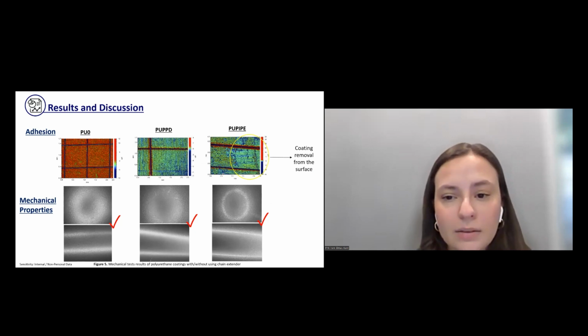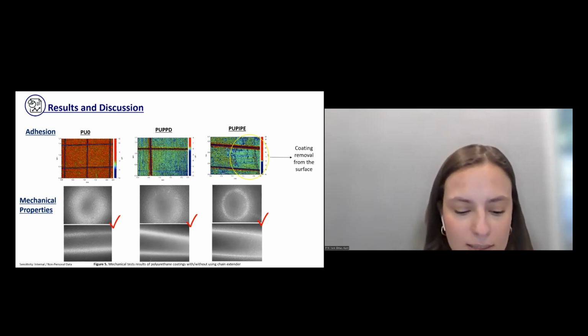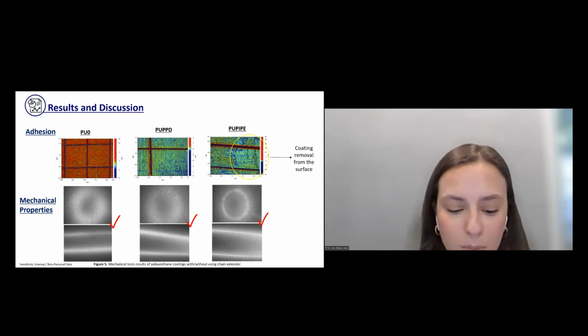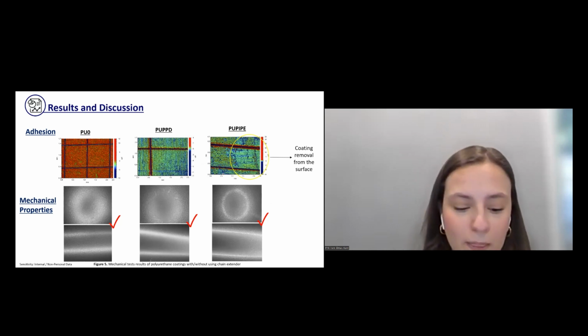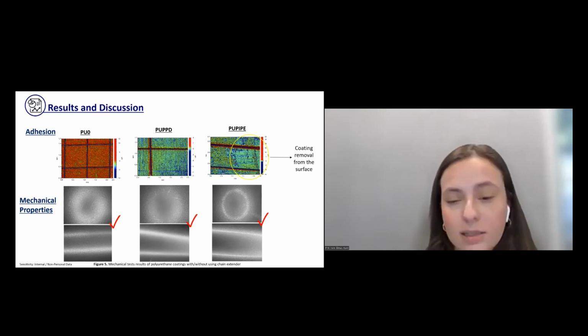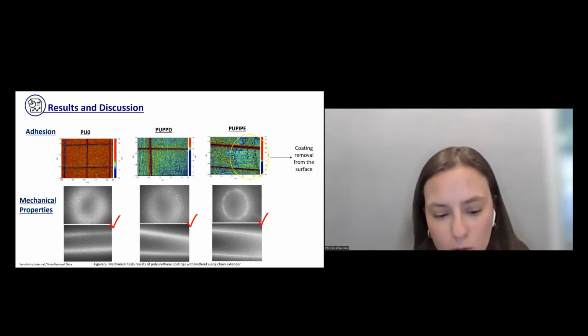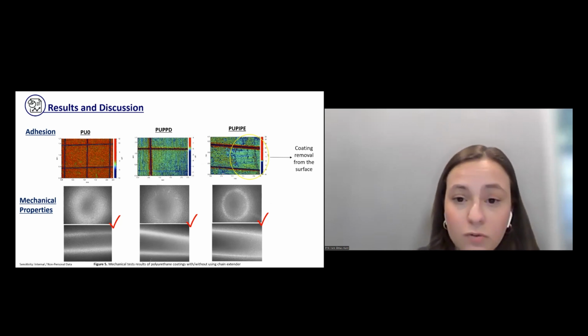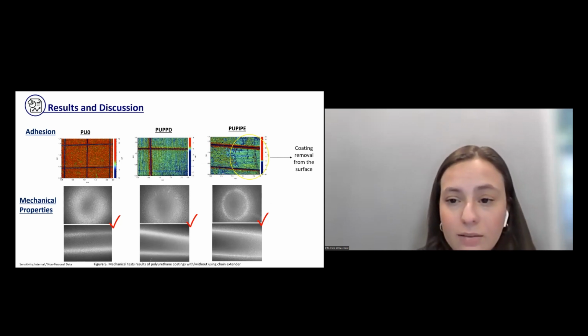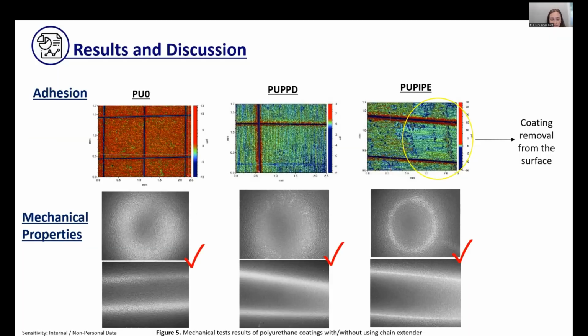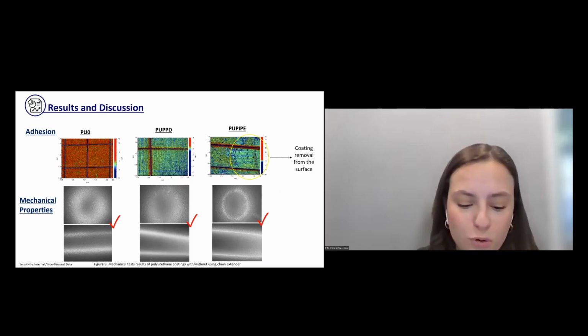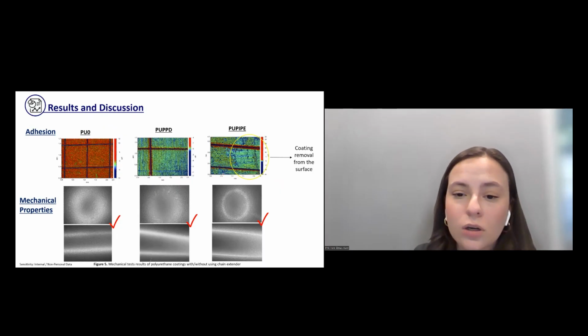The only sample that failed in the adhesion test was the one containing piperazine. This may be due to its low degree of cross-linking, as I said before, and hydrogen bonds are relatively strong intermolecular forces. In their absence, the interaction between the coating and the substrate may rely on weaker forces. And when hydrogen bonding is lacking, the overall surface energy may decrease, potentially leading to poor wetting and spreading on the coating substrate.